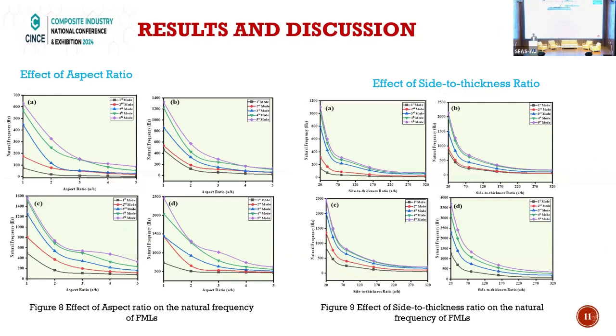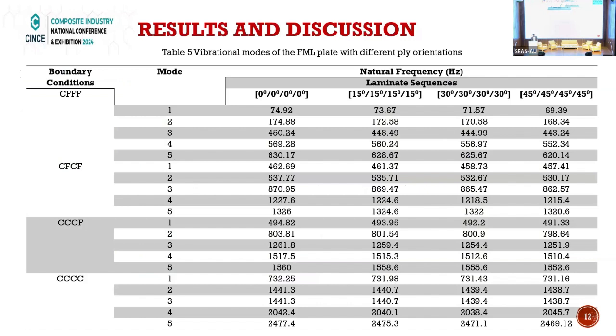And in figure 8 it has been observed that when we increase the aspect ratio, the natural frequency for all types of boundary condition decreases. Why? Because when we increase the aspect ratio, the flexibility of the structure increases, so natural frequency decreases. The same trend happens in the side to thickness ratio, as mentioned in figure 9.